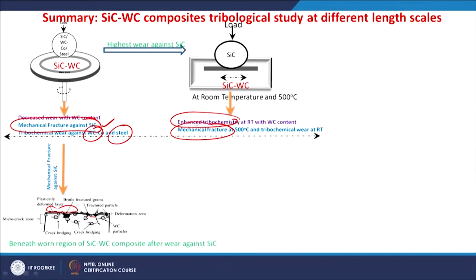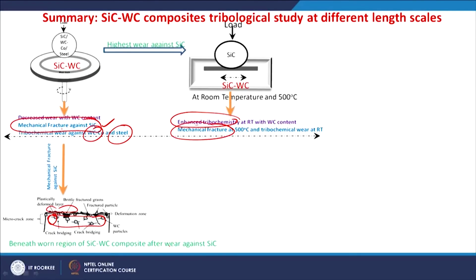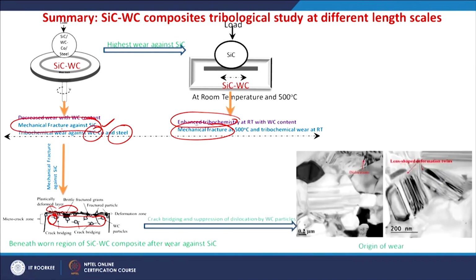subsurface study indicates the plastically deformed region as well as the cracked region, and the presence of the tungsten carbide is always beneficial in reducing the wear by crack bridging and crack deflection, so that the fracture is reduced, the wear is reduced. So, beneath the worn region, the silicon carbide tungsten carbide composite shows lesser or reduced propagation of the cracks because of the tungsten carbide particles present.